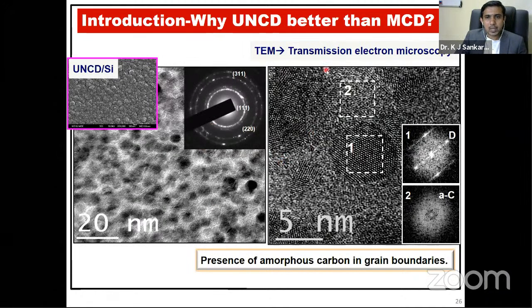And this is the high resolution TEM image acquired from this bright field image. So this is the magnified image. It shows a diamond grain of nearly 5 nanometer scale, and surrounding these diamond grains we can see there are some other phases. You can see the Fourier transform images acquired from this high resolution image. Number 1 shows the small diamond particle, and this is the Fourier transform image which represents the formation of diamond here.